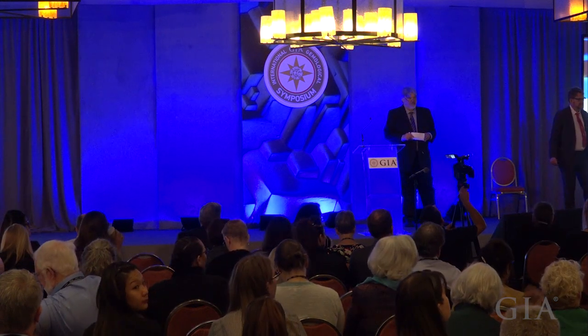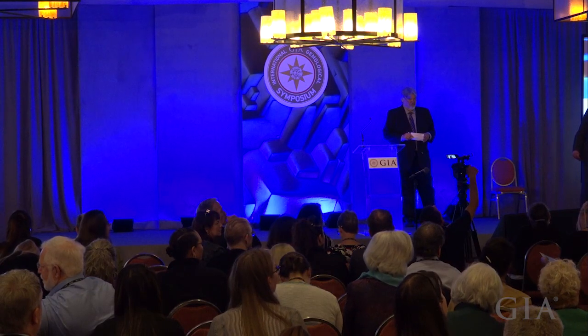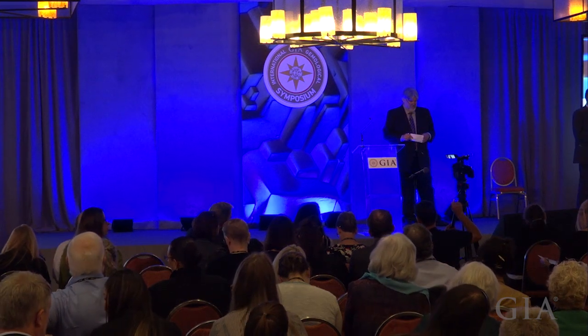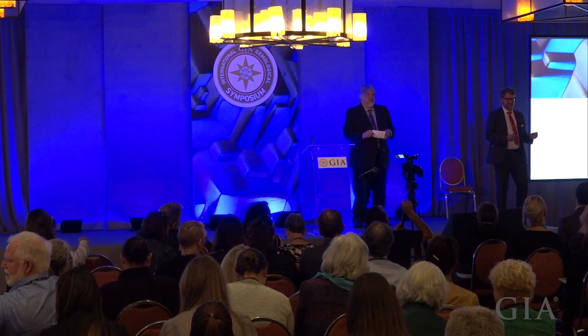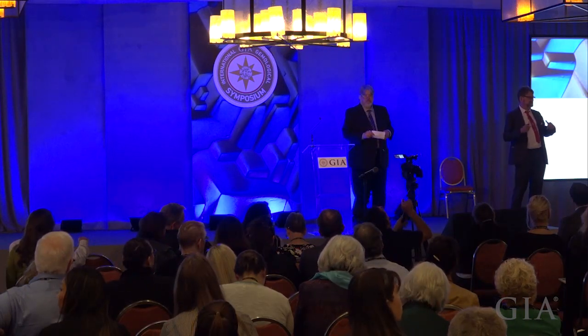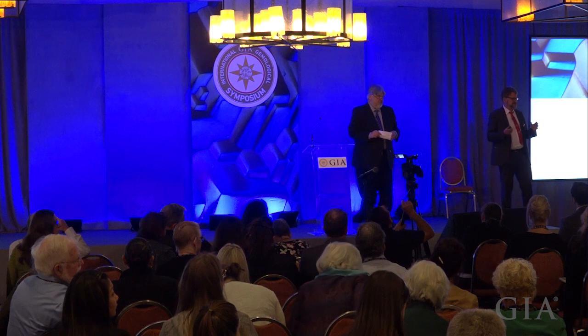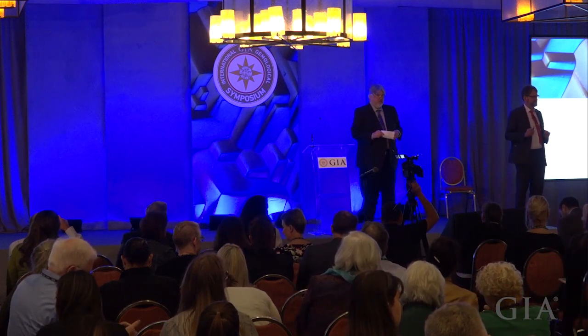Yes? How often do you confuse them with negative crystals? Can you speak louder? Sorry. How often do you confuse them with negative crystals? Oh, okay, well, it's something that we looked at first. We saw, could it be negative crystals? I mean, you have to have some very large ones to be able to observe that conveniently with a binocular. So already you start with a non-typical, which is not a good way to start. You'd rather start with a standard. And there was one Tanzanian sapphire where they were absolutely huge, and you could actually see the negative faces and measure them. So with much serendipity, they were measured. And lo and behold, they matched the faces of the rhombohedron. So that's why I'm reluctant to say they are negative crystals, because if you say a negative crystal, that relates to a growth phenomenon. This is a deformation phenomenon. So that might be to some degree misleading.